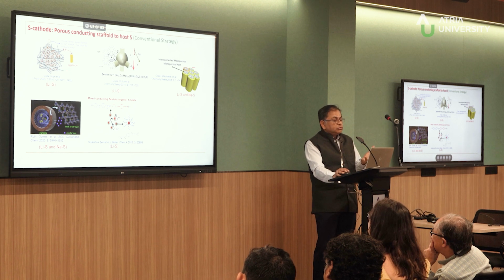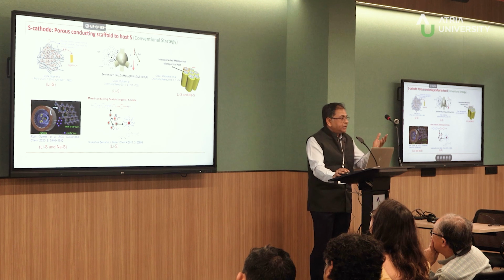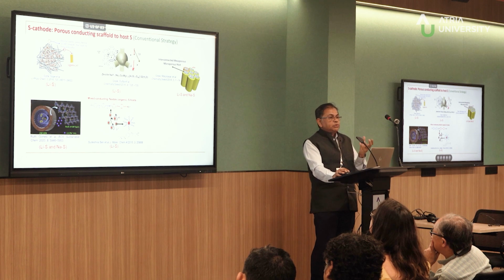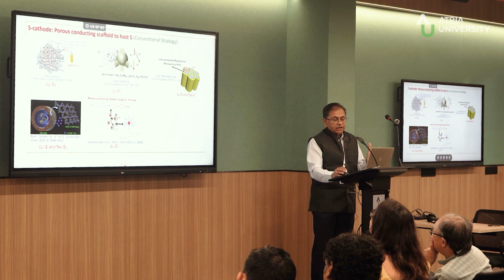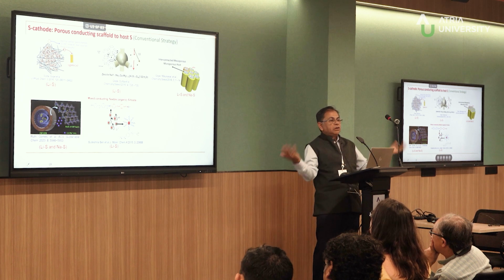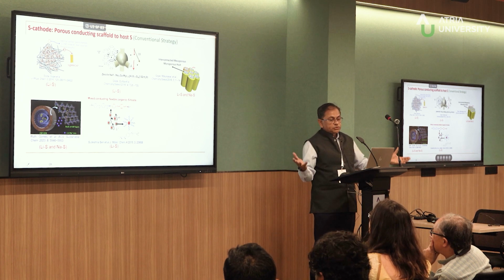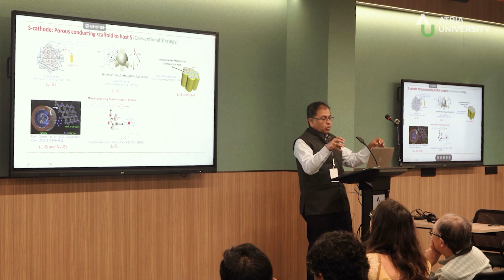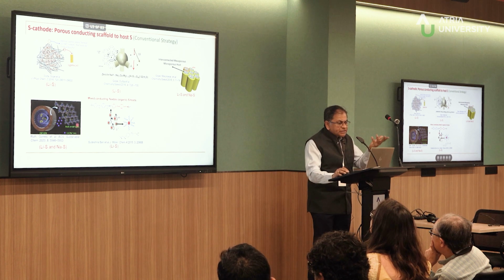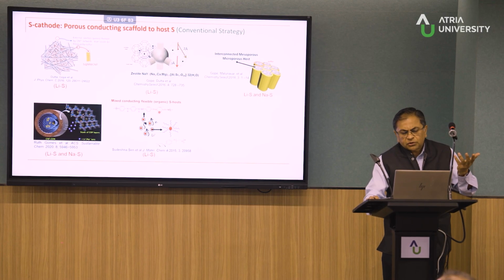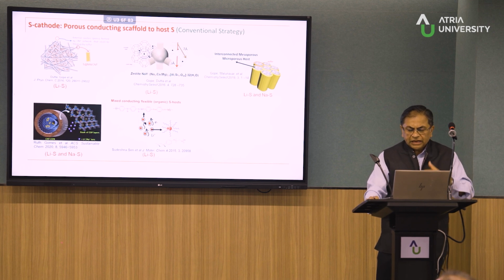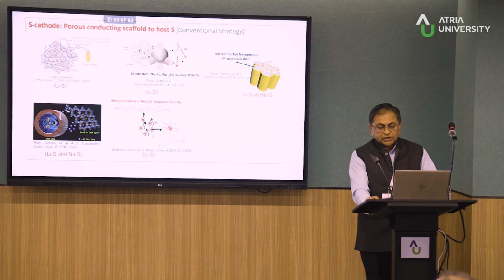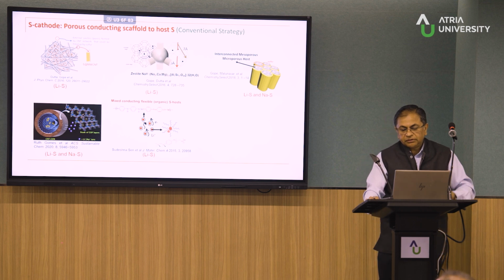Second, when we move to a very simple system like zeolite, you can get it anywhere. Zeolite has two different kinds of pores. Depending on where the sulfur is, sulfur has very strong confinement effects. So we have seen this kind of diradical formation, completely unfurling of the sulfur if the core size is bigger, or if there are less coordinating units. So these are some of the things. And then, of course, this is a very nice system. You're actually using polymer to wrap the sulfur, and that does all the entrapment of the polysulfur.